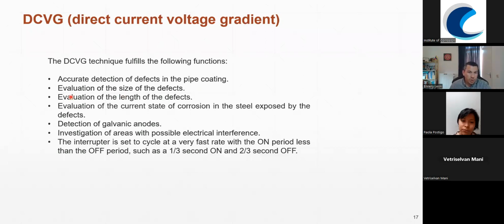It allows us to have an evaluation of the size of the defect, the length of the defect. That's also important, because if we're doing the CIPS, as I said, we will know that in one area we have a problem, but it could be a problem that is 1 meter long, 5 centimeters long, 12 meters long. And the CIPS doesn't give information about how long the defect is, but the DCVG does.